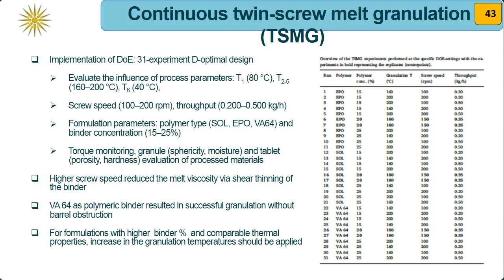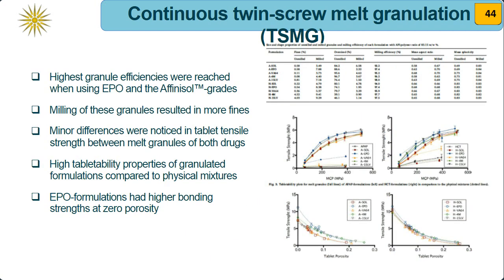It was found that higher screw speed reduced the melt viscosity via shear thinning of the binder, and thus VA64, when it was used as a polymeric binder, resulted in successful granulation without barrel obstruction. For all formulations with high binder percentage and comparable thermal properties, an increase in the granulation temperature should be applied in order to optimize the process. The highest granule efficiencies were obtained for the EPO and Affinisol grades, and the milling process of these granules resulted in more fines.